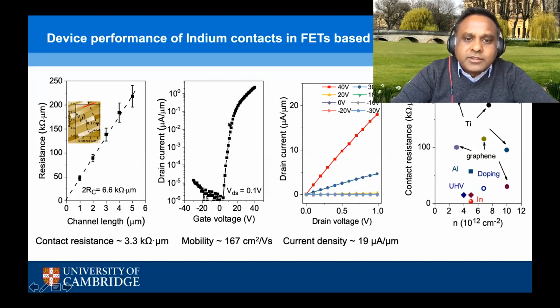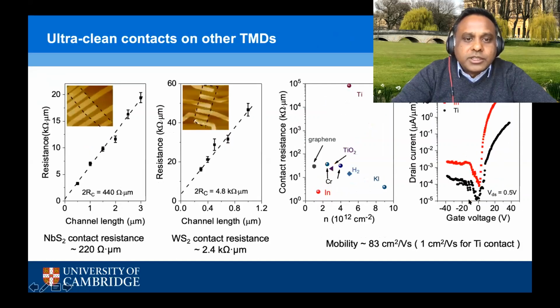And this translates into very nice FET characteristics with mobility values at room temperature in excess of 100 cm²/V·s, with reasonably high saturation current density. You see that the output characteristics are also linear, all suggesting that the contact properties are actually quite good. And if we compare the different methodologies that have been used to reduce contact resistance, we see that for indium, things are looking reasonably good.